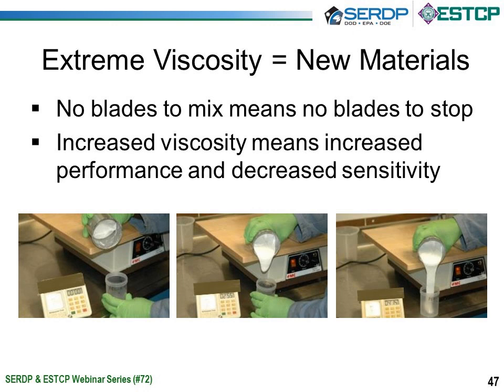Normally with a classic plastic bonded explosive, the time that it would take to flow all the material out of that small 500-gram container would probably be 30 seconds. And in some cases, we've made materials that you can measure the hardness of the material at the end of the mix prior to putting it in the oven to cure. And so essentially, if the material will move under the vibration that you can access using the RAM technology, you can mix it. If we move on to slide 48, we'll get into the meat of the presentation.